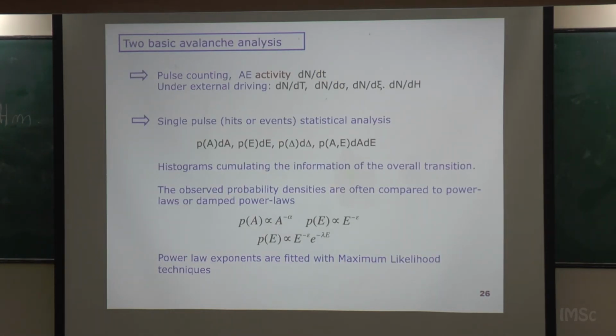Then with this information, there are 2 important things that we can do. One is very simple. It's just what we call the acoustic emission activity, or sometimes the pulse counting analysis. It's simply counting how many events you have per unit time. Only that, what we call the activity. Since we are driving the system at a known rate, the number of events per unit time can be translated into number of events per temperature range, if we are changing the temperature, or per stress, if we are changing the stress, or per strain, if we are straining.